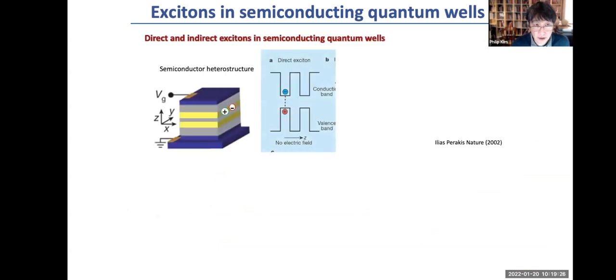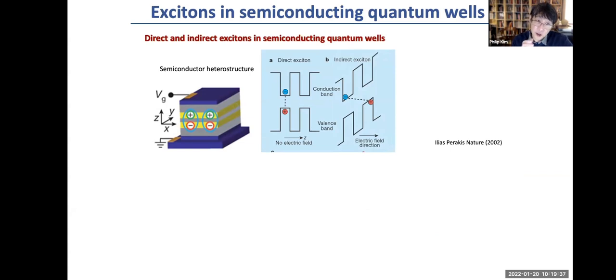Again, in the past two or three decades, this has been tried in the semiconductor heterostructure area. The important idea is, can we actually make the exciton live long? And there is indeed a way. In principle, if you have two quantum wells and create the exciton in one of them, bias this quantum well, you can separate the electron and hole and move them to live in different quantum wells. But nevertheless, these two quantum wells are really very close by. So the electron and hole, although they live in different quantum wells, can bind together and form this exciton.